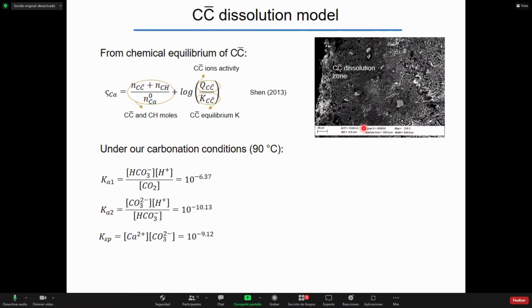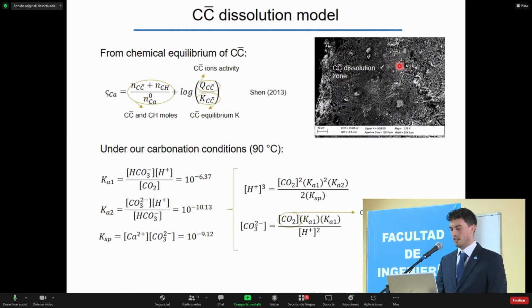Under our curing conditions of 90 degrees, we can determine the K constant of the carbonation process, and there are equations that relate this constant, and we can determine the concentration of carbonates as a function of the concentration of CO2 in the fluid. With the concentration of carbonates, we can determine the ion activity at a determined point of the cement, and thus calculate the value of sigma. If this value of sigma is less than 0, this means that there is no calcite present at that considered point.